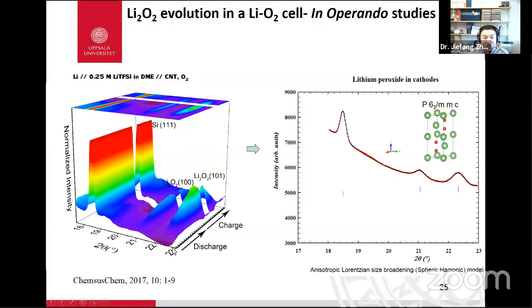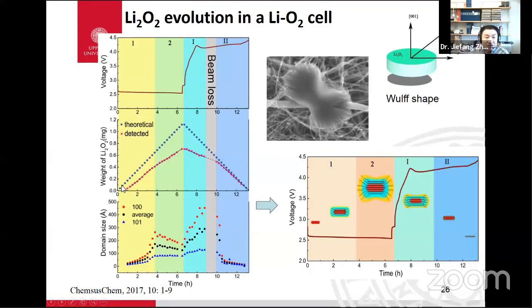So this is the first example for the new cell design, the model study, the pure fundamental research. You see that we run the lithium oxygen cell by using the commercial nanotube as the cathode without catalyst. During discharge, we can observe the lithium peroxide formation, and during charge, we could see the decomposition, the full process. The dots are the patterns we measured, and the curve we use the FullProf for refinement, for curve fitting by this model structure. What we get is the quantitative result for lithium peroxide formation and decomposition. This is a theoretical curve, and we also get the domain size information.